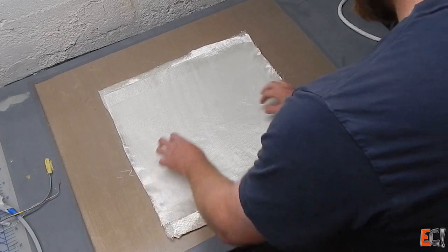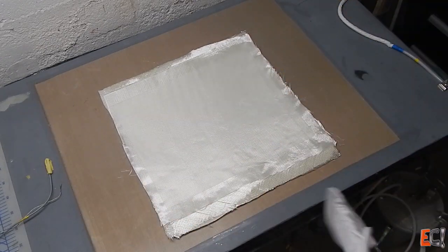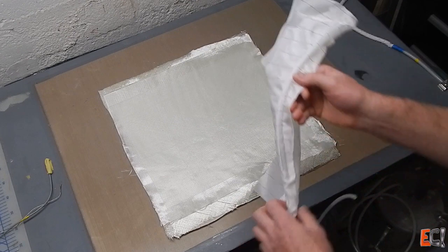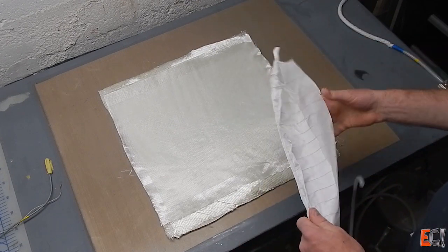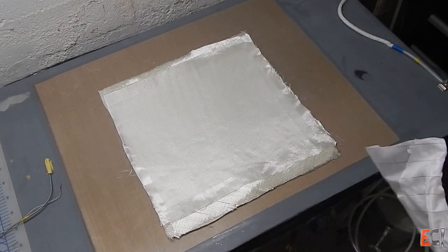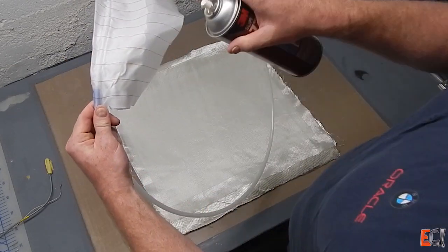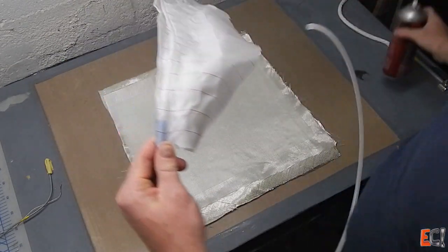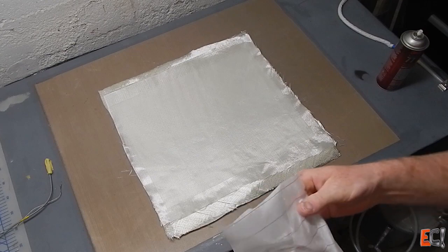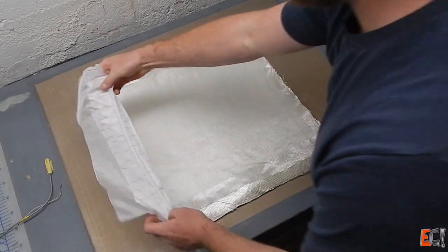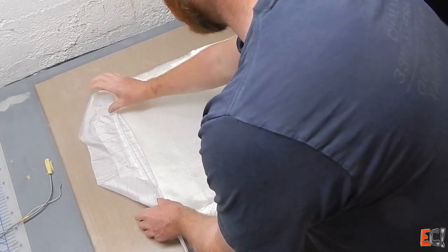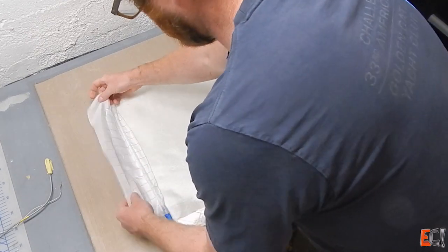And also it sort of demonstrates the lack of surface flow media, because any resin that flows has to flow through the fiber pack itself, and this will be a test of the permeability of that e-glass fiber. And for this test, I'm also going to use relatively fast epoxy.